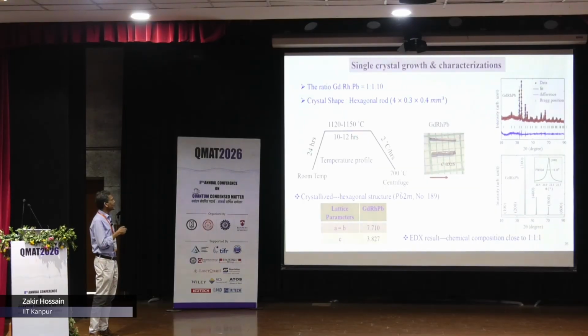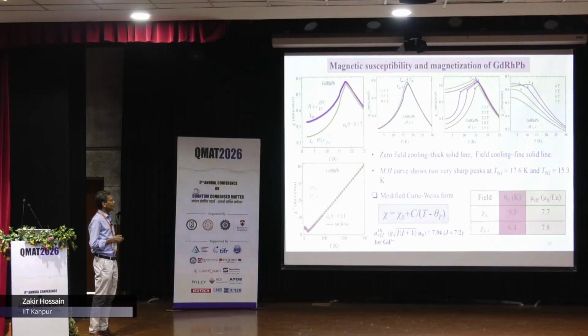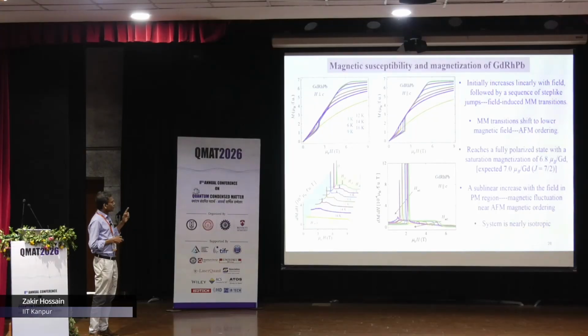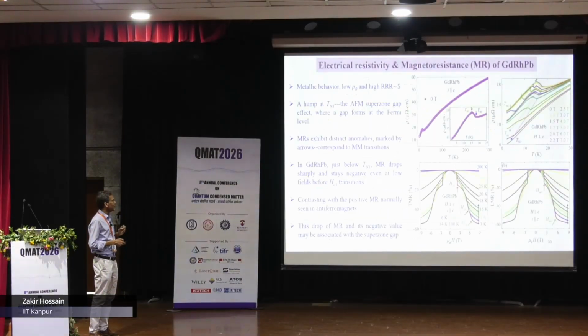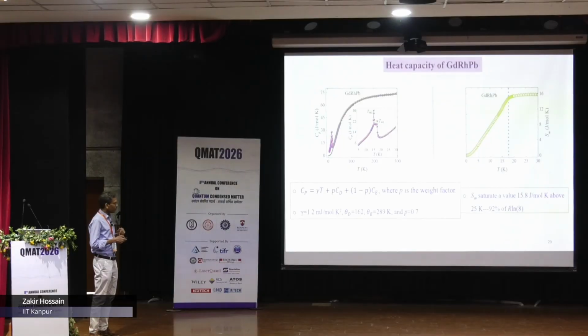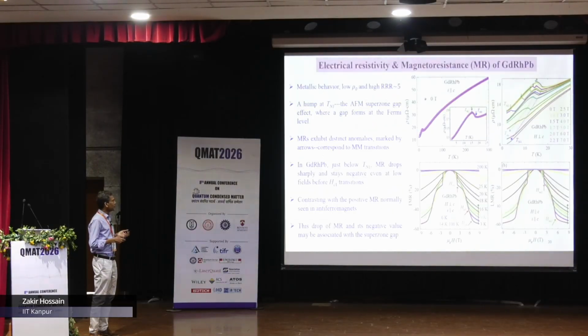Now I have only 5 minutes, so I will skip the summary part that I have already told. The second part is gadolinium rhodium lead. This compound is a pure spin compound. Good crystals were grown, and here I will just highlight standard things like antiferromagnetic ordering and susceptibility. The effective moment is what we expect for S equal to 7/2. But I would like to focus on one thing: with application of magnetic field, we find some field-induced transition, which is clear from this M versus H data, and dM/dH can give you at what field. Heat capacity also confirms the bulk nature of the magnetic ordering.